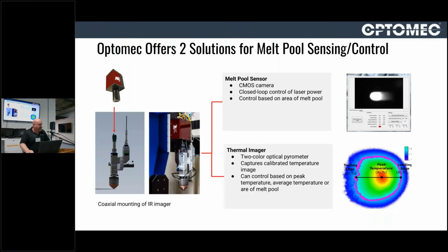And then everybody's talking about process monitoring or process control. So Optomec does offer two options for process monitoring and process control. The first one is the melt pool sensor. Optomec's used this for a long time. All the melt pool sensor does is it looks at the area of the melt pool and tries to maintain that by varying the laser power. Basically, if the part gets hot, it needs less laser power to maintain the same size area melt pool. So we can drop laser power as we're building up and pulling away from the substrate.